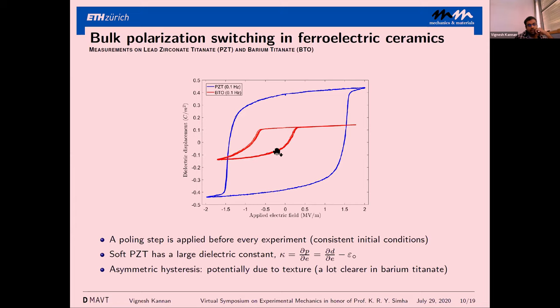The asymmetry is a lot more evident in barium titanate. The red curve is barium titanate and the blue curve is PZT. We can right away see, because of the sharper hysteresis and fast switching times, why PZT is more preferred for technological applications. People are trying to move toward barium titanate, which is why this field is open for mechanicians to enter right now — material design using these ideas is actively being pursued.